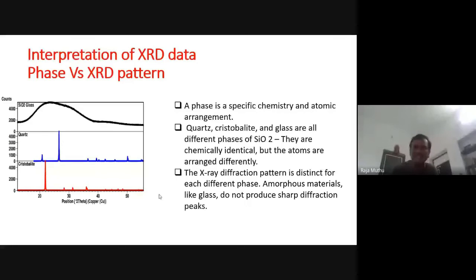So see here, this plot will give you three different forms of SiO2, and two are crystalline, one is amorphous. The glass is amorphous, and these two are crystal forms. Since these two, the red and blue, have sharp peaks, you can understand that these two substances have crystalline structures, whereas the glass has an amorphous structure, right?